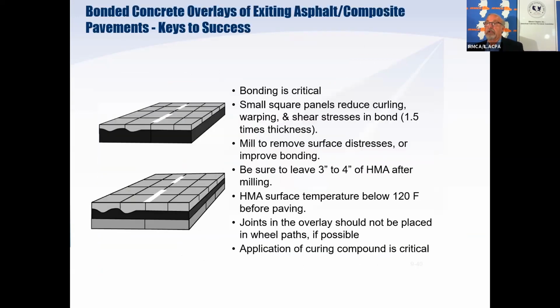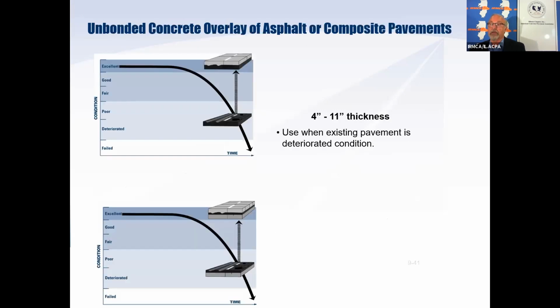So for bonded concrete on existing pavement, there are the key points, and we've talked through those. The only one I didn't mention up to this point is that you need to have the surface temperature of the asphalt below 120, because when you put the concrete on, there's a good likelihood that you'll stress the concrete with that high heat. So putting on a very thin mist of water and allowing it to evaporatively cool the pavement prior to placement is a good idea. But make darn sure you don't have water ponding.